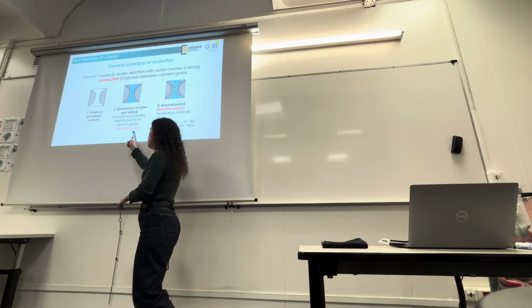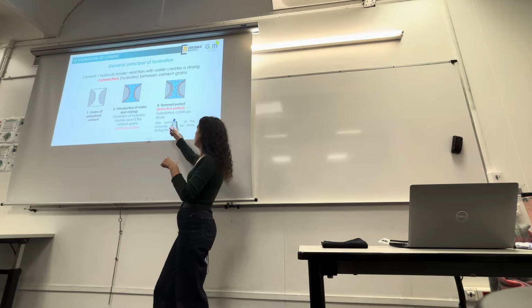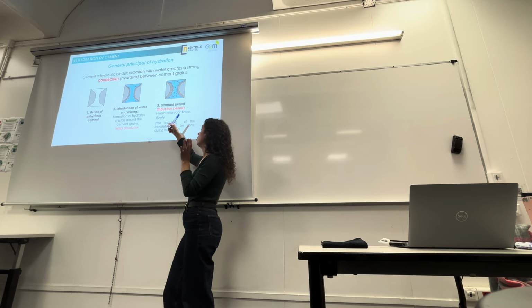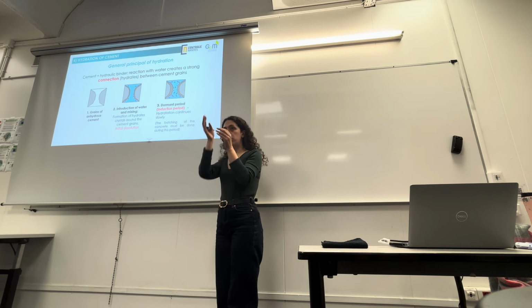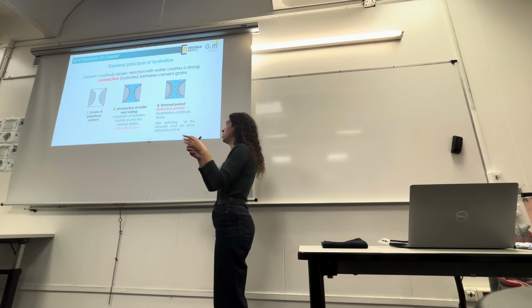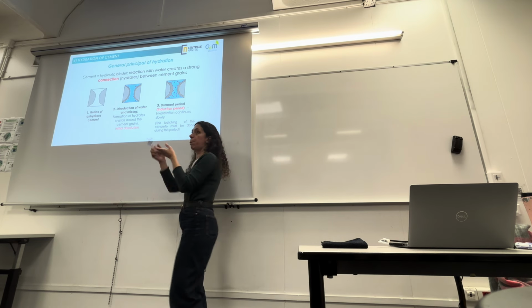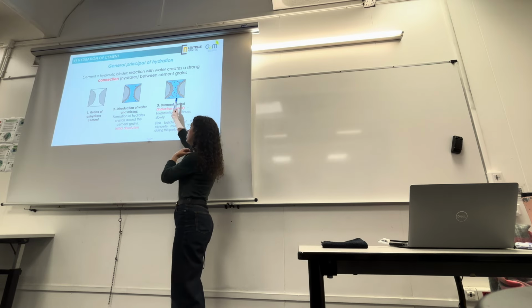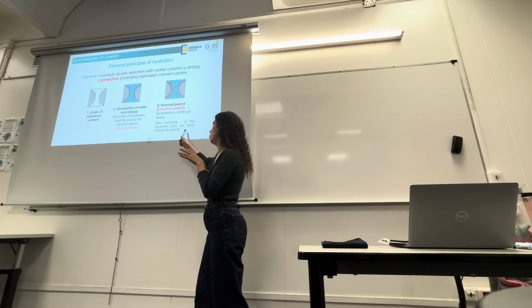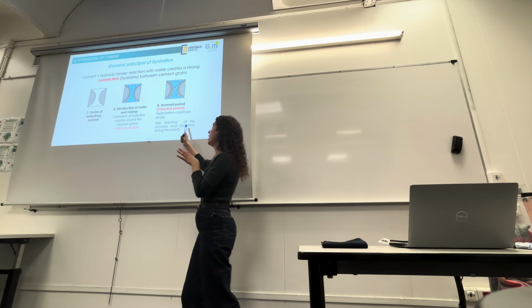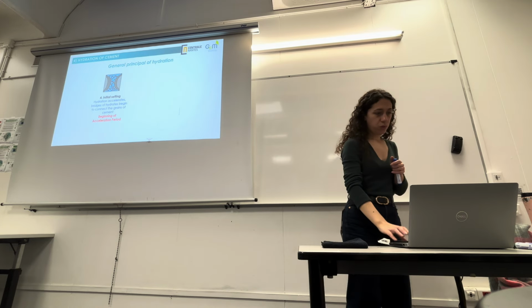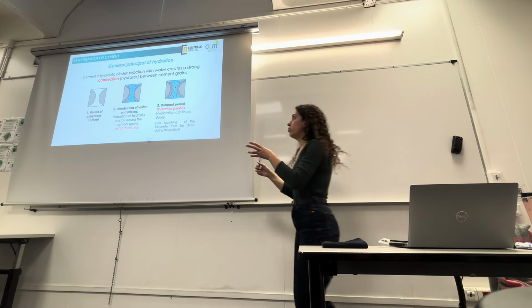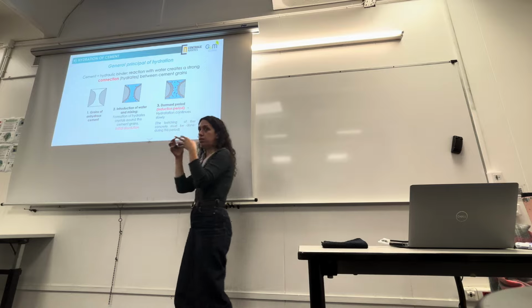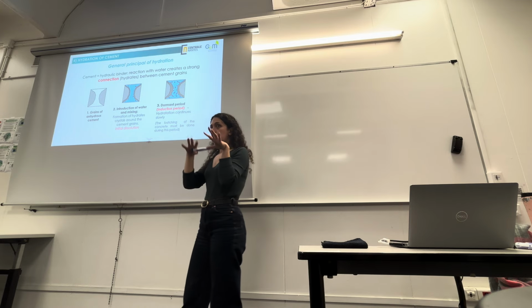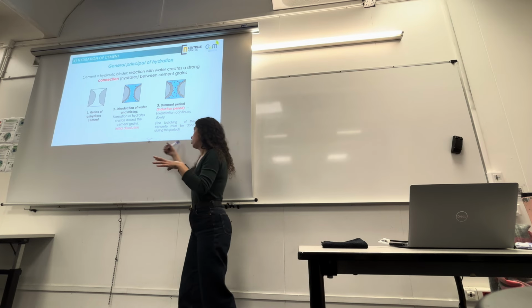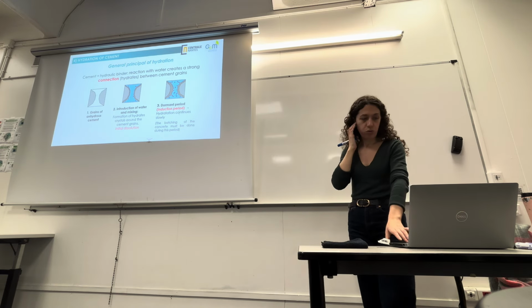So first you have the dissolution and the transformation, and then you have the hydration that continues slowly, and you have the formation of the layers of hydrates around the grains of cement and they start connecting. But at this point, you have your hydration, but the grains are not connected. So this is the time when we can do the batching of the concrete, because after that you will get to stage 4. So that's why we call that the dormant period. The hydration is happening, but your cement is still fluid. You can use it, you can batch it, and do whatever you want to do with it.